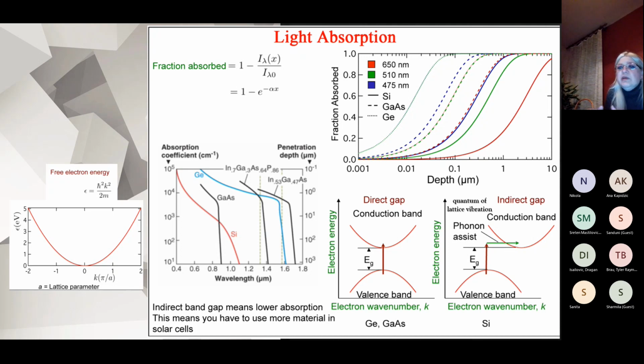And in semiconductors it will always be opposite. For instance, antimony sulfide, which I use in solar cell applications: its crystalline shape is direct gap, opposite to silicon, but its amorphous shape is indirect gap, and that will always be the case in semiconductors. So if your crystalline shape is direct, then amorphous will be indirect, and the opposite.